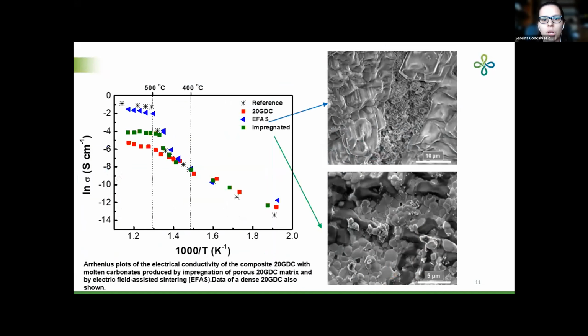This is the Arrhenius plot of the electrical conductivity of those samples. In blue, we have the electrical conductivity of the composite membrane produced by flash sintering, by infiltration in green, and a pure dense Gadolinia-Doped Ceria in red. It's interesting to notice that the electrical conductivity of the dense GDC exhibits mostly a linear behavior in the entire temperature range, showing that the electrical conductivity of the sample is dominated by the conduction only of oxygen ions.